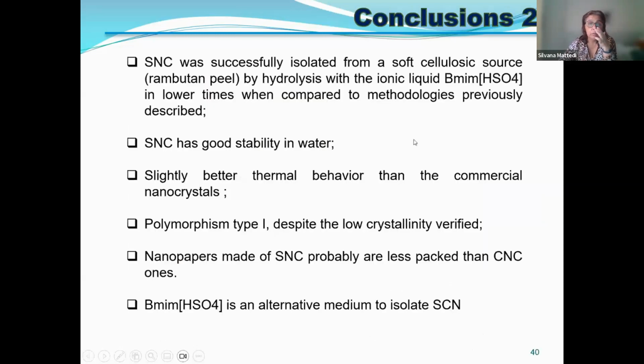So we draw the conclusions that the spherical nanocrystals (SNC) is successfully isolated from a soft cellulose source such as rambutan peel. We could isolate also different materials from other sources, but we would not put everything, so it would be too long. We use the hydrolysis with the protic ionic liquid, and we can do it in a short time, more quickly. You can obtain the cellulose with the ionic liquid.